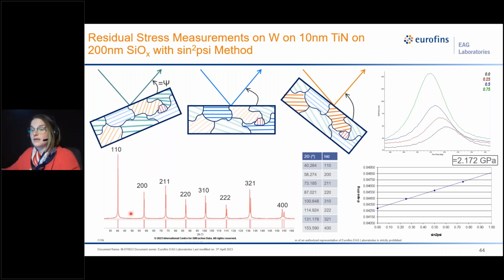So what that gives you is that, for example, in this material, the D spacing, the 2 theta peak, is going to shift with respect to the stress. And it's more sensitive to this at higher 2 theta. So we're going to look at this peak out here at about 130. What we can see is that at different tilts, the D spacing position is at a different value. Each of these values is plotted with respect to the tilt, which is the sine squared psi, and what you get is that slope. So if you know your material, you know the elastic modulus and Poisson's ratio, which means we can calculate your residual stress. In the case of this sample, it was 2.17 GPa.